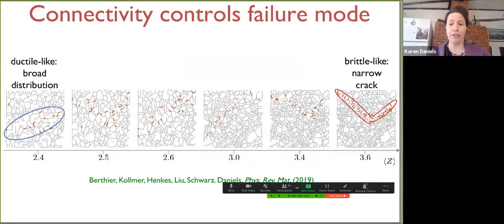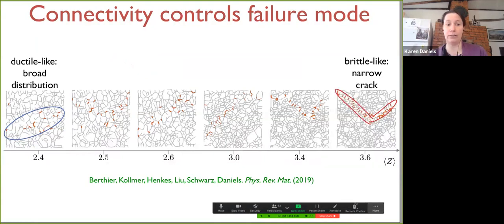And the first movie I showed you was all the way to the left. It was a bunch of failures happening all over the plastic. An engineer would call this ductile-like. There's a broad, distributed failure. It's a bit of an ooze. And as you can see, as you increase the connectivity, we get more and more crack-like behavior. This is what an engineer would call brittle, and you see distinct cracks where things fail along well-defined paths.